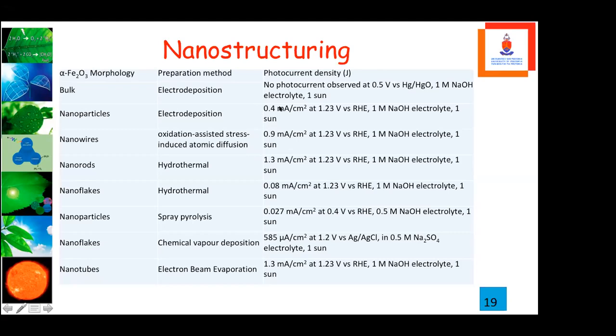Then we have also achieved nanoparticles, and you can see that our photocurrent is growing gradually from 0.4 milliamps, to 0.9 milliamps, to 1.3 when you use nanorods, after we have grown those nanorods using hydrothermal methods. With our nanoflakes, in one experiment the photocurrent was too small, but in another experiment in the lab it was improved a little bit. We still believe that the nanotubes and the nanorods are doing better as compared to other nanostructures.